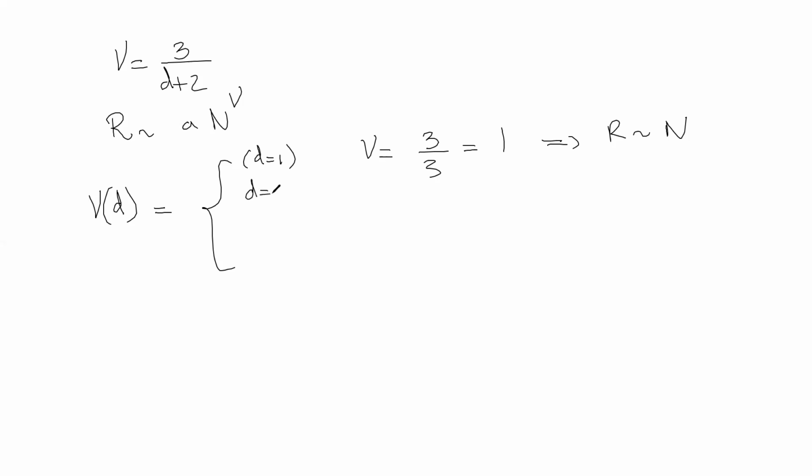Okay, so nice. D equal to 2: you have an exponent which is 3/4, which is bigger than 1/2, despite the fact that in 2 dimensions, a random walk is also given by a 1/2 exponent. So really here, the repulsion interaction is making the chain a bit more swollen. D equal 3 is the case of interest in our typical world. And there we have something which is 3/5, so it's equal to 0.6. So again, it's larger than 1/2, slightly larger.